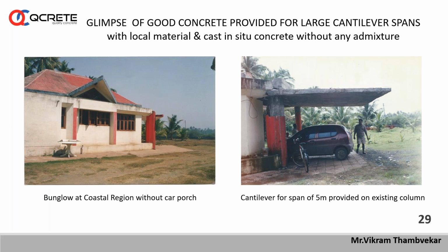Here I want to explain that even in a local area, with local material, we can use very good fresh concrete by controlling the water cement ratio and proper proportioning of the local material. And this site is very close to the sea, in a coastal area in Raigad district of Maharashtra. This particular canopy is still there without any problem, without any cracks. Of course, a very light section was used. The thickness of this cantilever slab is limited to 150 mm to 100 mm, and the grade of concrete is not more than M25 or something.